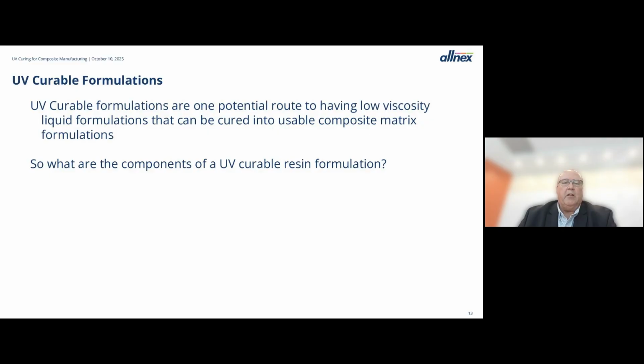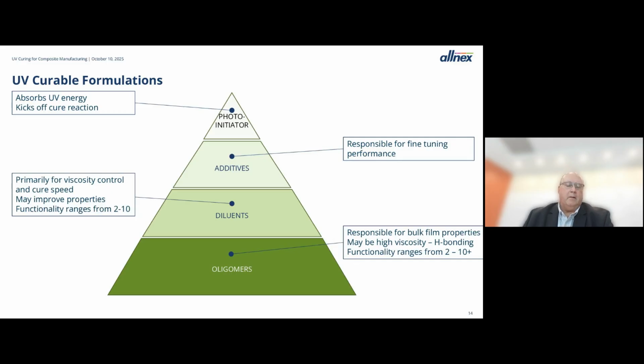So if you think back to the beginning, UV curable formulations are a potential route to starting off with a low viscosity blend, hitting it with UV energy, and creating high molecular weight materials that form your composite matrix. But what goes into a UV curable formulation? So this triangle gives a rough idea of the components and their relative quantities. Oligomers will always form the base of your formulation. They're responsible for bulk properties. So whatever the main property you want in your material, or the main couple properties, generally drives your selection of an oligomer. Diluents are primarily used for viscosity control.